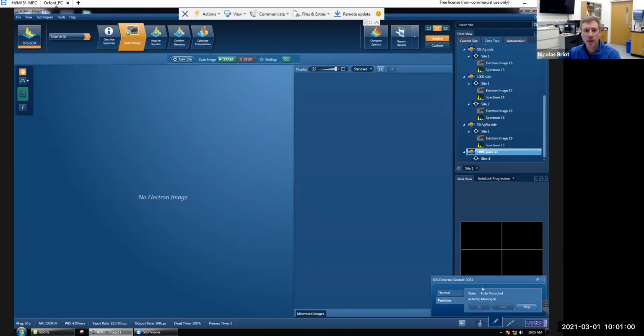I don't know if I mentioned that, but I retracted the EDS detector before I vented the machine. It's a good habit not to have the EDS detector inserted. Many new generation EDS detectors are windowless, and that sudden change in pressure from high vacuum when letting nitrogen gas in to vent can cause damage. Even if you have an older style detector that can handle the change in pressure, I wouldn't take the risk. Those detectors are expensive, so I retracted the detector and I just inserted it back in.